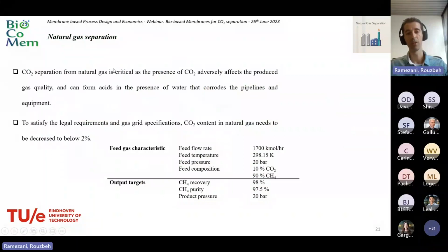So let's check another application. We also checked natural gas. So almost the same, but a different gas composition, which is from 90% methane to increase purity to about 97.5% purity at 98% recovery. So it depends on your gas grid. You need your specification. This can be changed. For example, here we decided to be at 20 bar, but it could be even 40 bar.